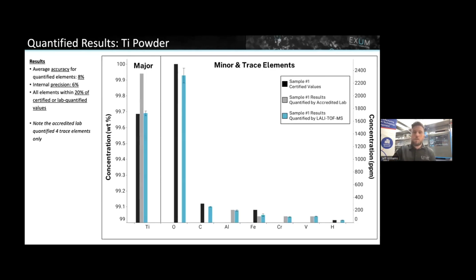And really what this comes down to is, let's say you're an additive powder provider and you have some new titanium, and we know titanium loves oxygen, and we want to make sure that it has the right amount of iron in it. With one standard, a single point calibration curve, and an unknown powder, let's say this is something that you just printed with and you want to do a quality check on this powder, or it's a solid part after you make it. You want to check the oxygen level before, you want to check the oxygen level after. Carbon, aluminum, iron, chromium, vanadium, even hydrogen in here. We did all these elements simultaneously.